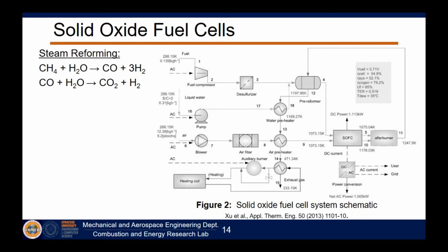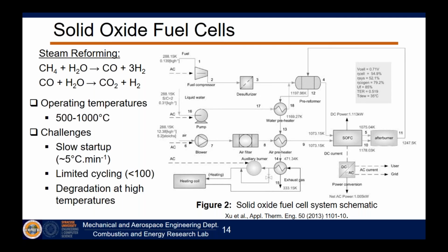What are the challenges? Well, they operate at 500 to 1,000 degrees Celsius, okay? And when they operate at that temperature, because this is a ceramic material and it needs to be sealed very well, we typically start up at a rate of about 5 degrees Celsius per minute. Okay, so 5 degrees Celsius per minute up to 500 degrees. You can do the math really quick, right? That takes a long time. This isn't a car. You don't just hop in and you turn your system on and it just goes. It takes a while for these things to heat up. So I want you to remember that 5 C per minute because that becomes very relevant later.